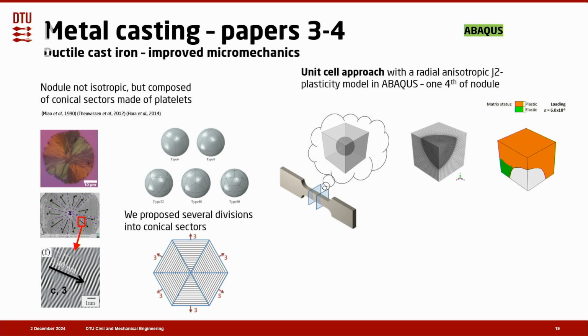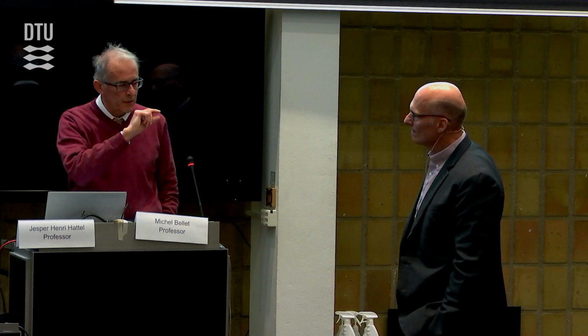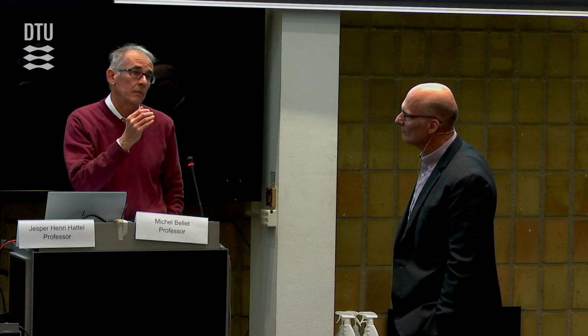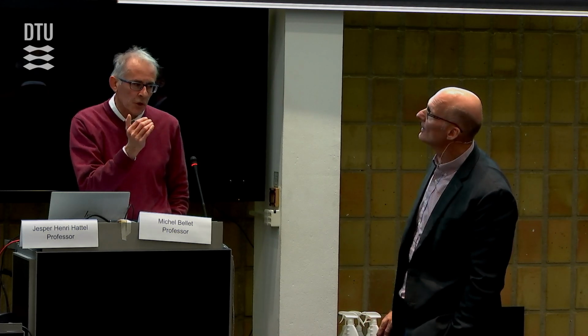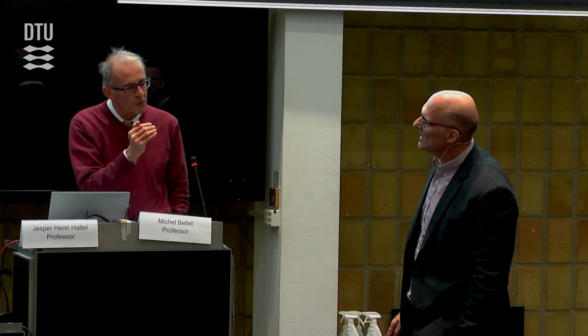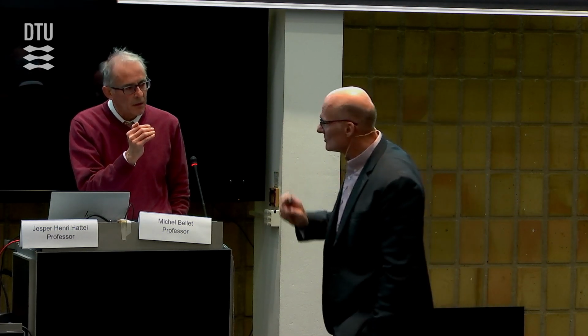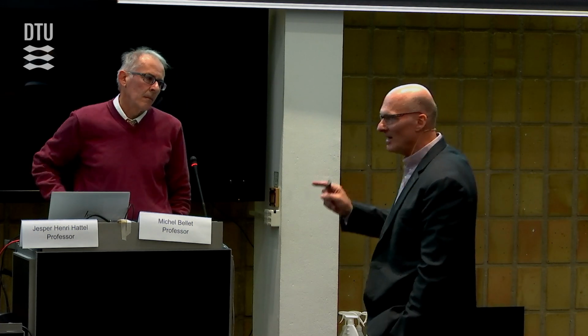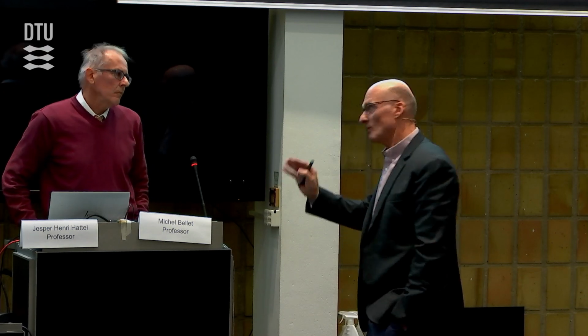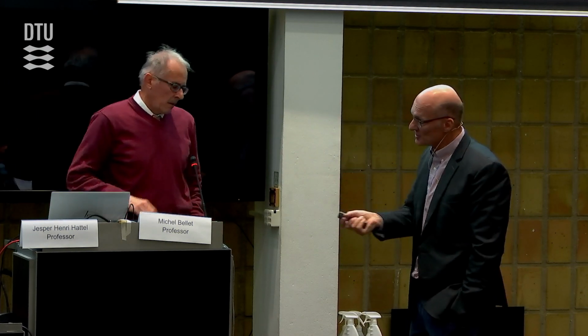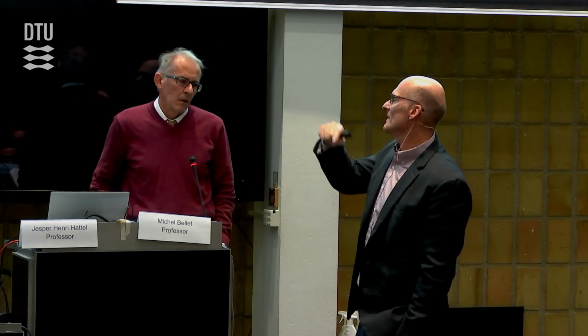Because I thought that on top of that, the surface of the nodule, which is in contact with the matrix, had a specific structure, and that it was also important to take that into account. Yes, but that was taken into account as well. That's true, but it is less important than the other factors. I think so. But we didn't evaluate them by isolating them, so I cannot tell whether it was the surface description or the fact that it was in conical sectors and platelets in combination with residual stresses.